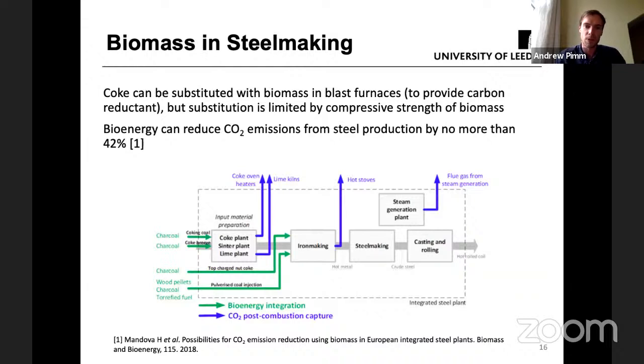As I said before, one option is to replace the coke in blast furnaces with biomass, but you're limited by that technical limitation of the compressive strength of biomass. It's been found that bioenergy could reduce CO2 emissions from steel production by up to around 40%. So in terms of very deep decarbonisation, getting down to very small levels of CO2 emissions, or effectively net zero, it couldn't be used on its own. However, it could potentially be used with carbon capture and storage.